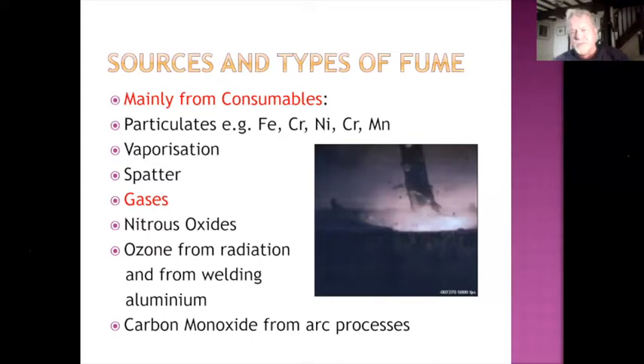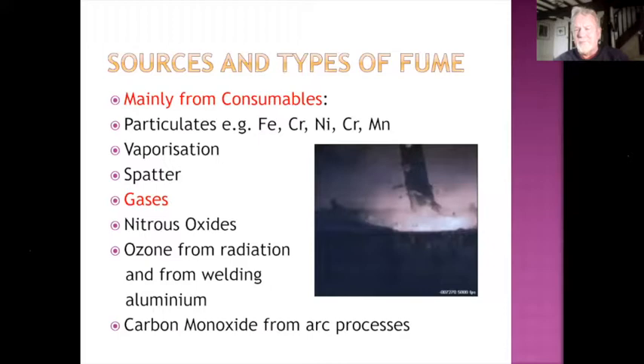Cellulosic electrodes have certain ingredients in them to intensify the arc. And what that does is it also releases a considerable more content of carbon monoxide. Also, the other thing that you need to be aware of is how you store your consumables. If they get damp, then they can fire and they can create more carbon monoxide whilst they're drying out, as it were.